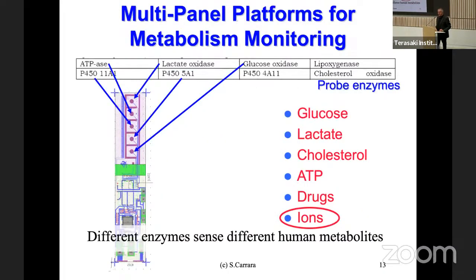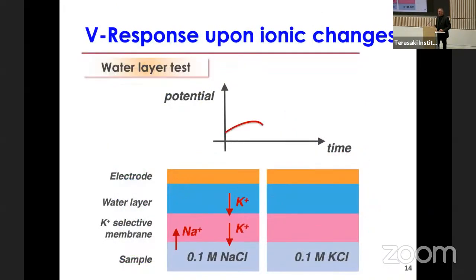Another interesting case is the one of ions. Years ago, we collaborated even with Mehmet and Ali on this field. In this case, we can use measurements of open circuit potential. If, for example, in this cartoon, potassium goes up or goes down, we have a variation in the potential we measure at the interface. However, as the cartoon shows, we typically have very much drift, and this is a very well-known phenomenon all around the world. I will show you in a while how we could solve the problem of time drifting in ion sensing by open circuit potential.